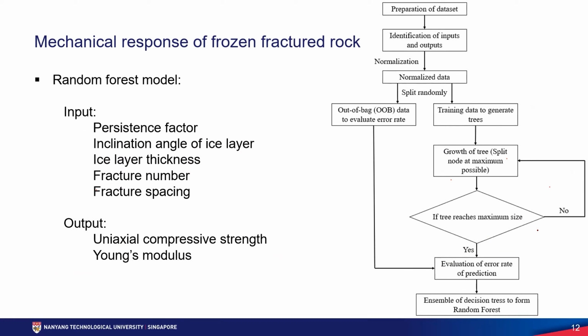Here we use a random forest model to predict the mechanical behaviors of the frozen fractured rock. We actually tried many machine learning algorithms, such as neural networks and support vector machines. And finally, we found that the random forest is the best to predict the mechanical behaviors of the fracture network. And here we use 5 parameters as the input: persistence factor, inclination angle of ice layer, ice layer thickness, the fracture number, fracture spacing. The persistent factor is defined as the sum of the fracture trace over the total length of the skyline. Right, we have the other parameters together as inputs, and use uniaxial compressive strength and Young's modulus as the outputs.